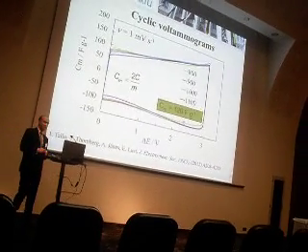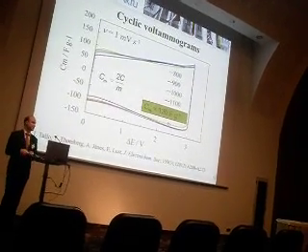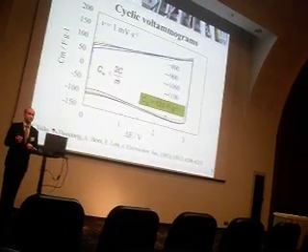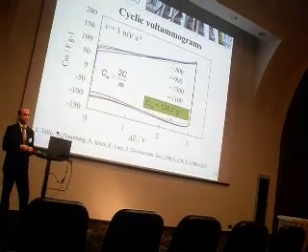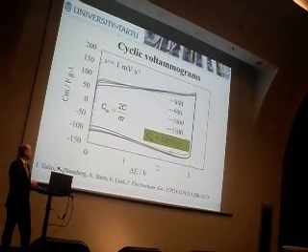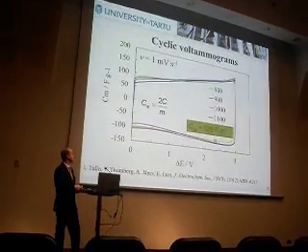And the results. Well, we found from cyclic voltammograms that the materials synthesized at different temperatures all show nearly ideal capacitive behavior, and they don't vary much with synthesis temperature. They're all almost the same. And the specific capacitance we calculated from these voltammograms was 120 F per gram.